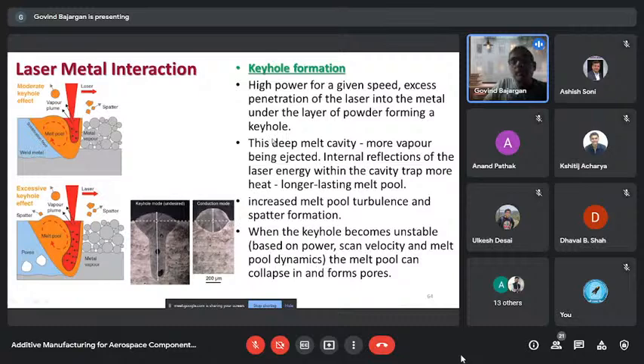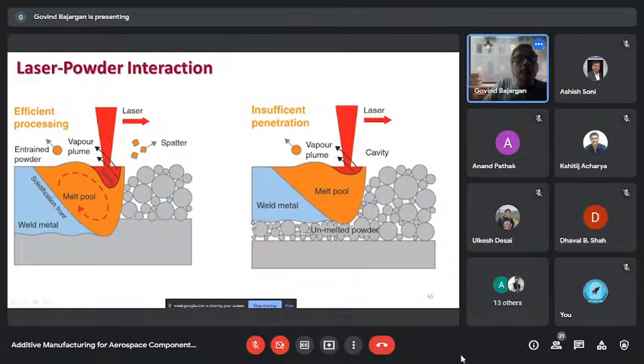And if my power is too high for a given speed, we can end up in a very deep melting zone, because the energy will be so high that some evaporation will happen, and when this liquid pool collapses, the vapors get encapsulated, and there may be a keyhole formation. This is why there will be pores because of keyhole formation. Okay, so these are the laser powder interactions.